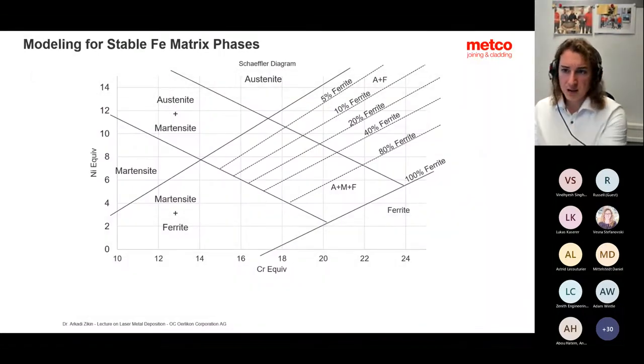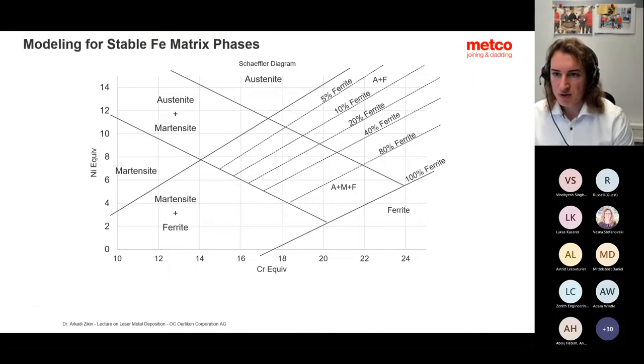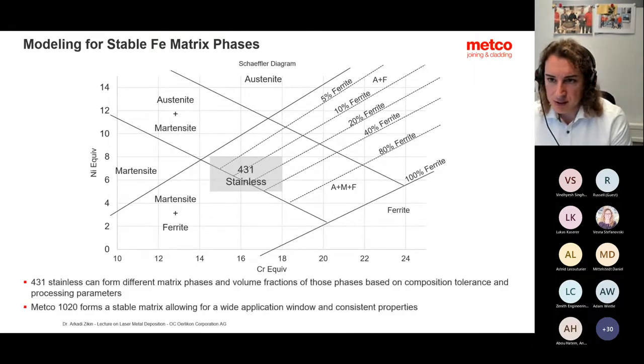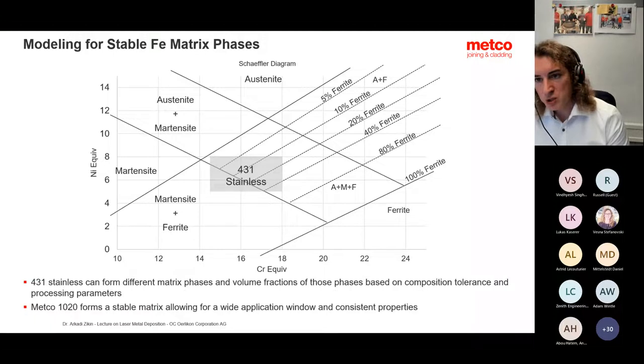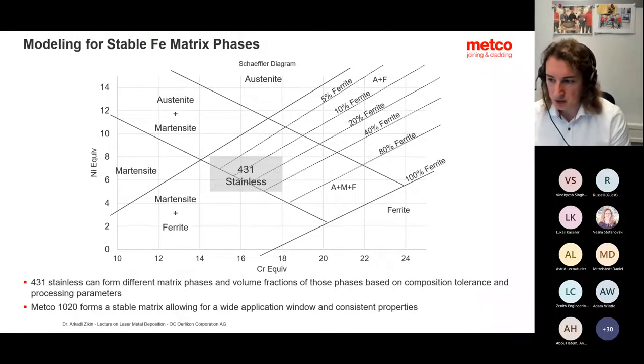So going back to the modeling, imagine 400 series stainless steels or martensitic stainless steels. Depending on your process parameters, your dilution, and also the initial composition of your material, because the nickel percentage might vary, chromium percentage might vary. After deposition, you may end up in a ferritic environment, or in martensite-ferrite conditions, and this all might have a dramatic effect on your corrosion properties and also on your hardness properties.